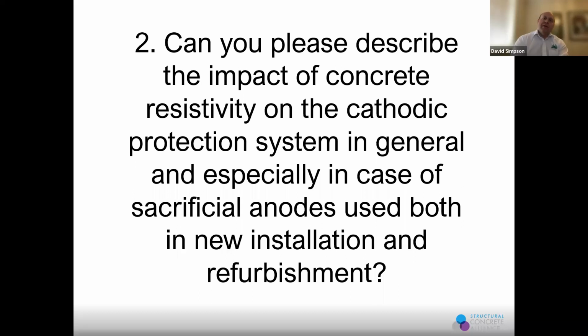Thanks, Dave. Okay, so this is a really, really broad question. I'll try and break it down into its three component parts. The first one is concrete resistivity is never stable over a structure. It's going to vary depending on the environment and on the element of the structure. Normally that's related to moisture content and to the amount of chloride that's already got into the structure. Both of those really reduce the resistivity of the concrete, and we have to take them into account when we're looking at any cathodic protection system.